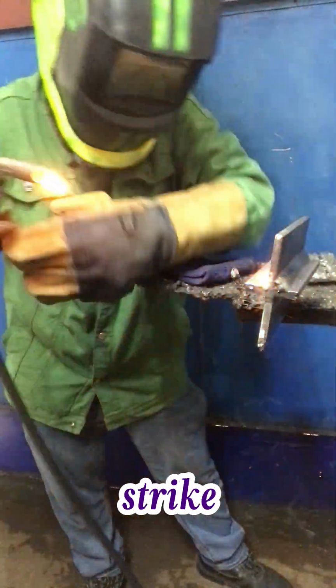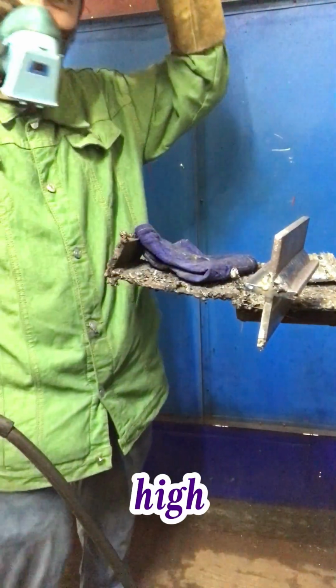Listen closely when you strike the arc. You want a steady, high-pitched bacon sizzle sound. If it pops loudly, increase your voltage slightly. If it hums loudly without sizzling, your wire feed speed is too high.